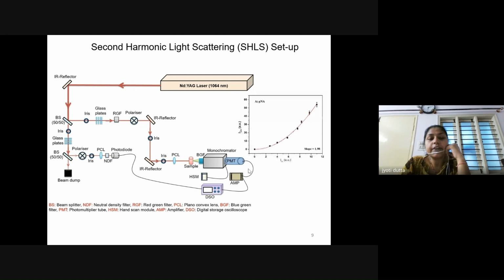We checked using a probe, para-nitroaniline, which is a standard molecule for optimizing the second harmonic. We did the power dependence measurement, where we vary the power of the incident radiation and check the scattered signal using the detector, and we plotted the scattered second harmonic light intensity versus the incident radiation. We observed that the slope of this power dependence plot is 1.98, which is very close to 2. So this ensures that the scattered light we are investigating actually has a quadratic relation with the incident light.